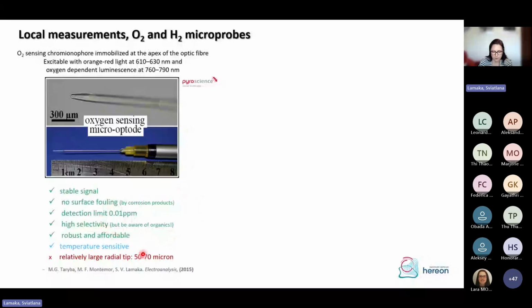But for flat samples, we can combine 2 or even 3 microprobes. In this case, this is an optode together with a pH-sensitive microprobe scanning across this sample, and we can then get distribution of local concentration of dissolved oxygen and pH.